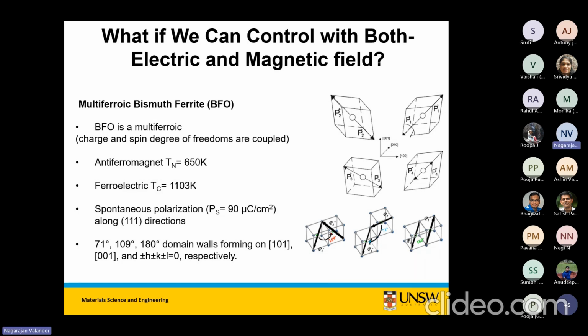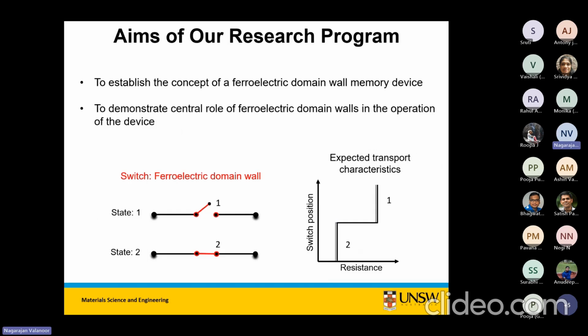So can we then engineer the ferroelectric state so that we get only these kind of domain walls that conduct? Right? That was the purpose of this topic, ferroelectric domain wall memory. Why do we want to do that? Because we thought that if you have a ferroelectric domain wall as a switch, a domain wall that conducts, then if the domain wall exists and the circuit is closed, you'll have a low resistance state. The domain wall can be erased. If the circuit is open, you have a high resistance state. So you have a very easy 2-state memory, a 0 and a 1 state.